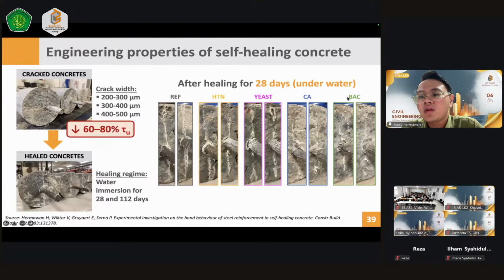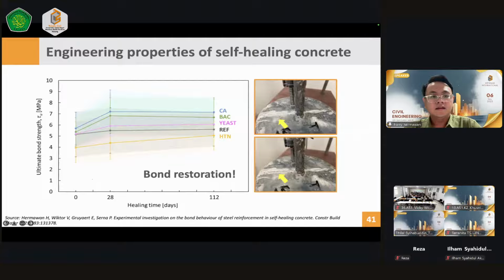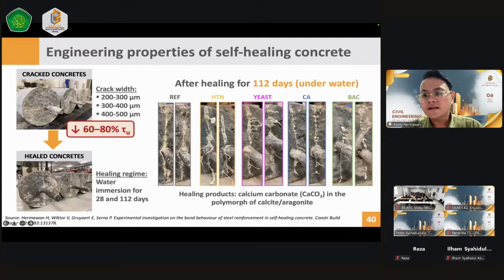And what's going on if we prolong the healing time? This is only after 28 days. So what's going on after 112 days? Yeah, the crystals will grow so much. The minerals will grow abundantly until they do not stay only inside the crack, but come out from the cracks and give a lot of stalactite structures. This healing product, we can also confirm later with FTIR, is calcium carbonate in the polymorph calcite or aragonite.